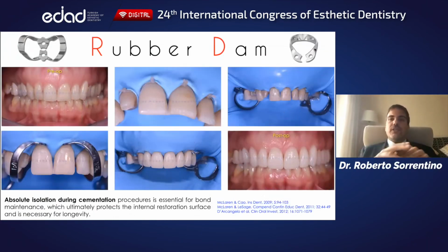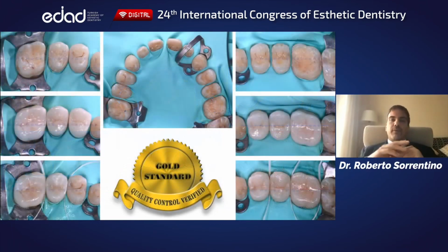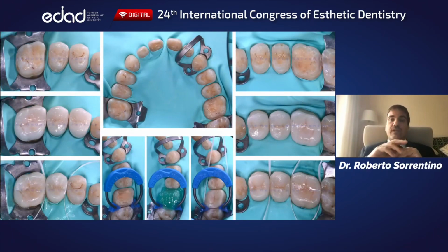It is well known that the achievement of good adhesion relies on the management of clean surfaces. In this perspective, isolation by means of the rubber dam is crucial to prevent any contact with blood, saliva, and other contaminating agents. The careful control of moisture is an indispensable prerequisite to obtain the best bond strength values, which can be reduced by up to half in the presence of surface contaminants.